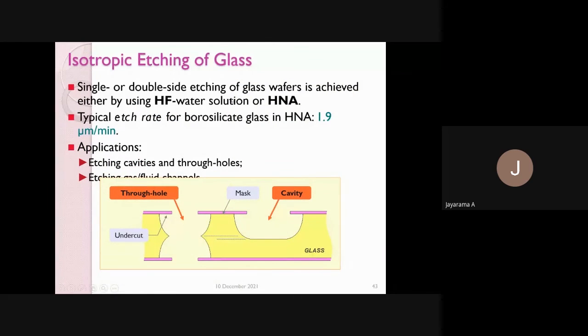This is about isotropic etching of glass. Single or double side etching of glass wafers is achieved either by using hydrofluoric acid water solution or a combination of hydrofluoric acid, nitric acid, and acetic acid (HNA). Typical etch rate of borosilicate glass in HNA is 1.9 micrometer per minute. The applications are etching cavities and through holes.